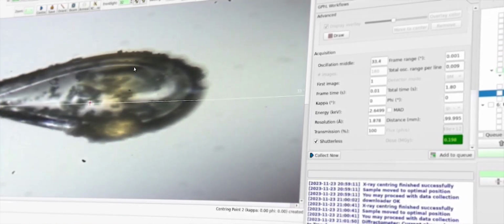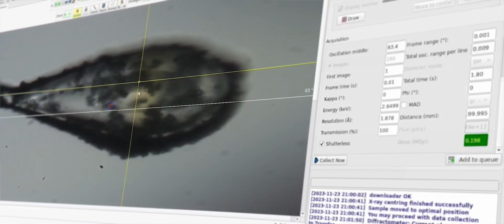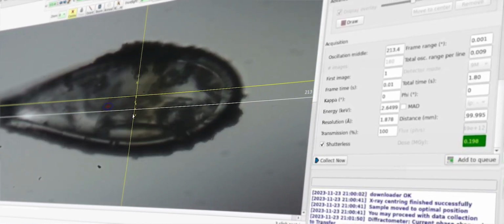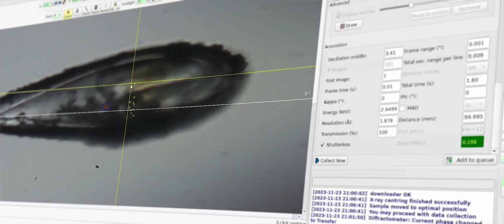The sample zone of a crystal can be aligned with the beam either optically or with X-rays. Optical alignment is done by clicking at a particular zone of the sample at multiple orientations. Due to refractive effects, a layer of mother liquor can distort the visual position of the crystal, making its optical alignment difficult. For such cases, we have developed a method that accounts for such refractive effects explicitly and allows us to model the sample environment in the process.